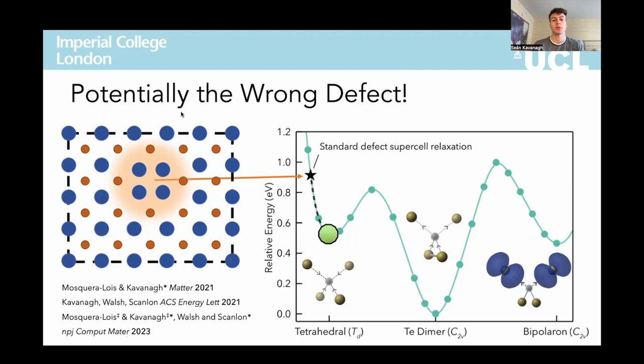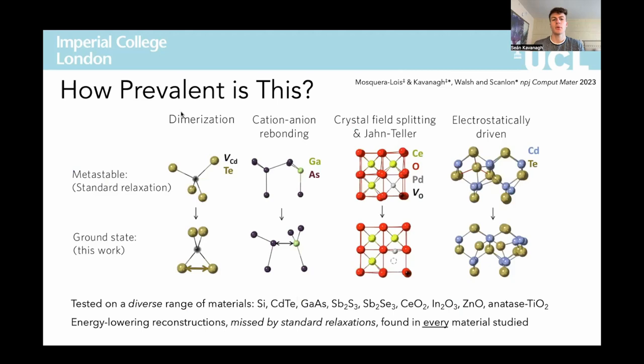A question we might first ask is: how prevalent is this behaviour? We tested this by applying our defect structure searching method across a wide and diverse range of materials and their defects. In doing so, we found this behaviour to occur in every material that we looked at — energy-lowering reconstructions that are missed by the standard modelling approach — with a variety of underlying physical driving factors.